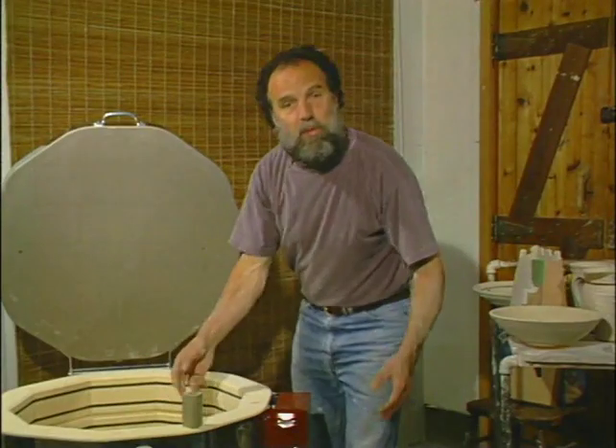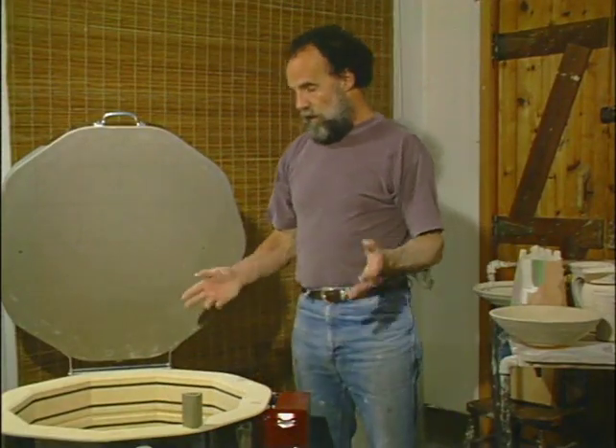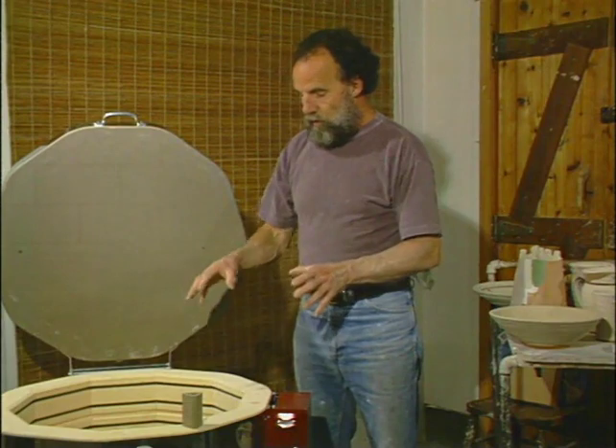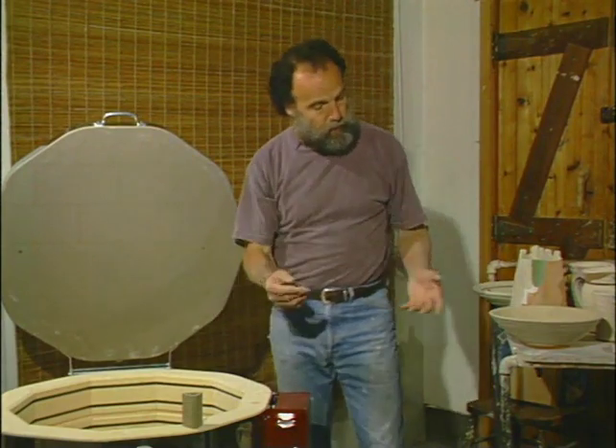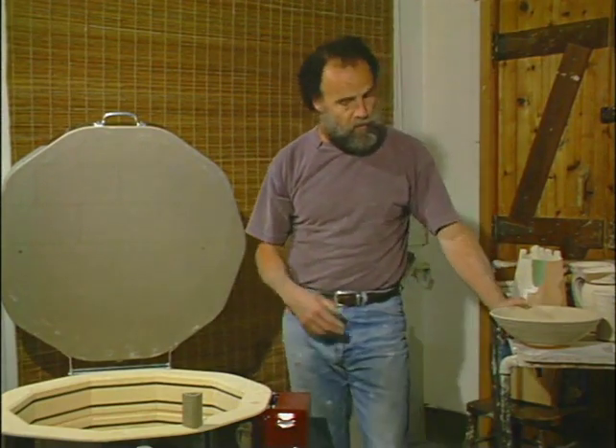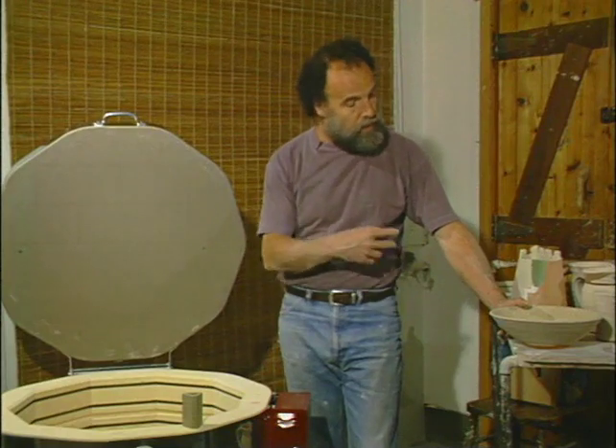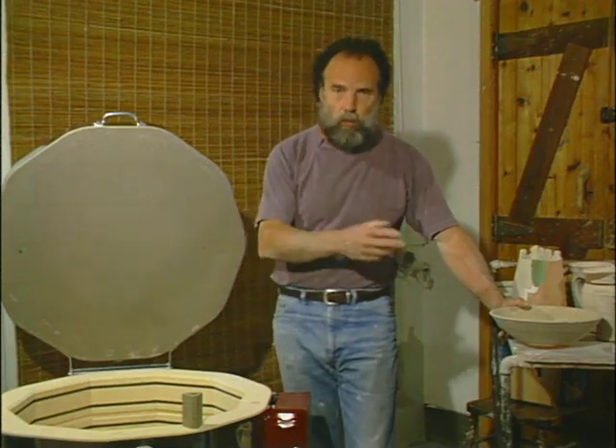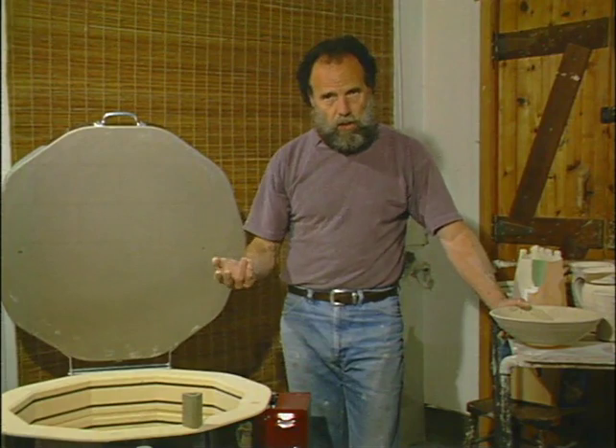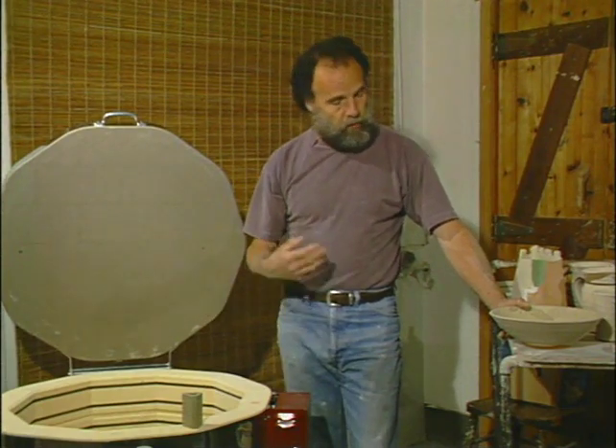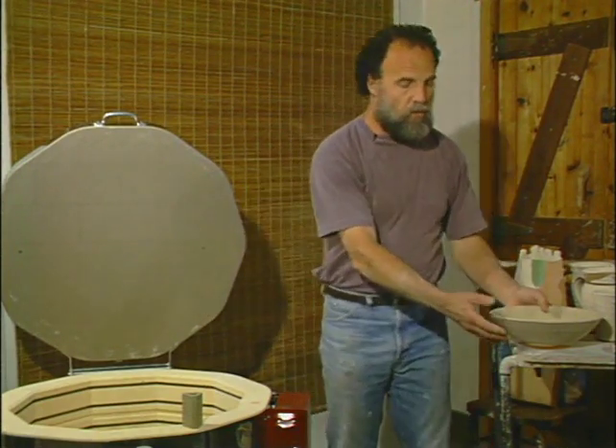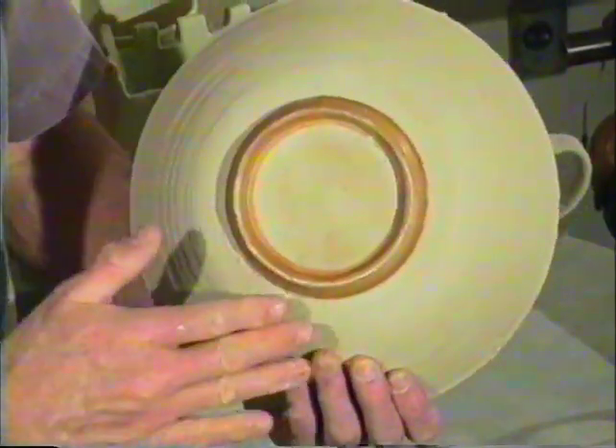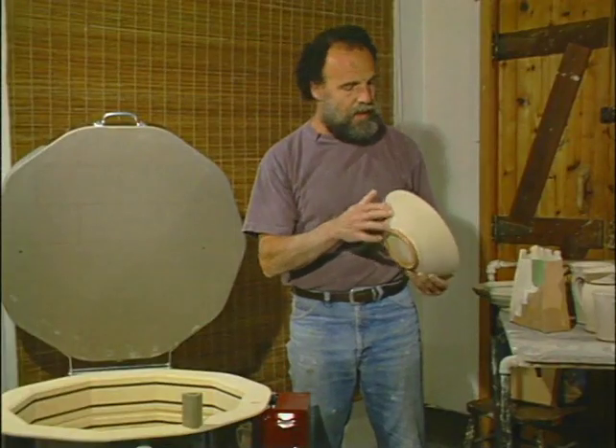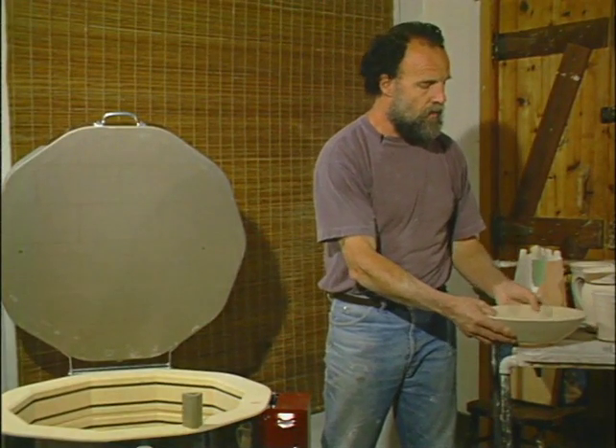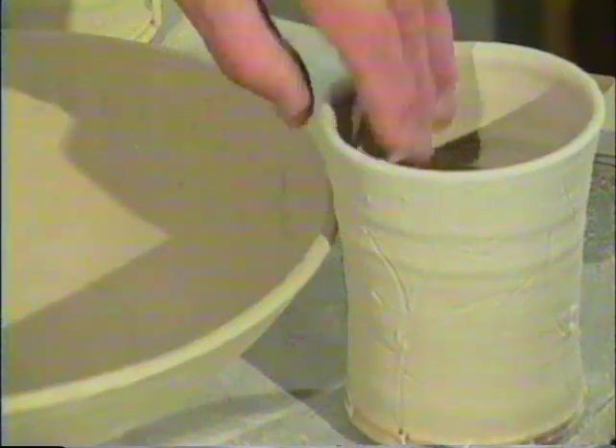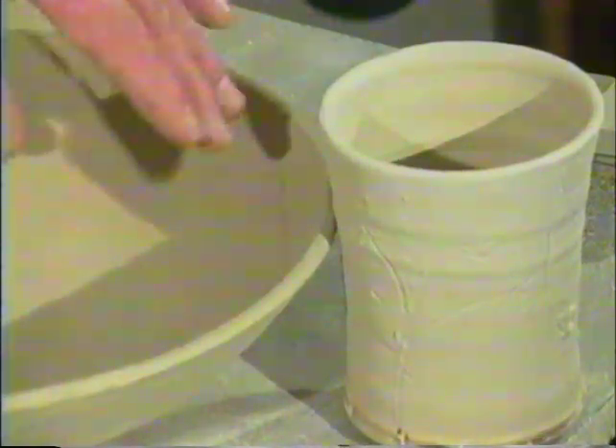Okay, now as we place the pots in the stack now, we've got to be aware of a couple of things. The first is, of course, that this is a glaze firing. These pots are mostly glazed, so of course they can't touch one another. At the top of the firing, when you've achieved temperature, these pots, which are now covered with a chalky dry substance, of course will be covered with a sticky liquid. So what you can't have are pots touching one another, because they'll fuse together at the point of contact.